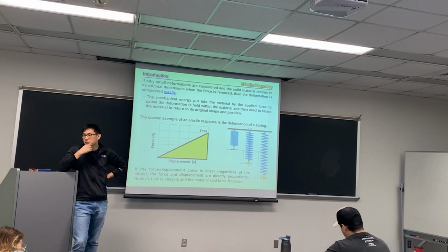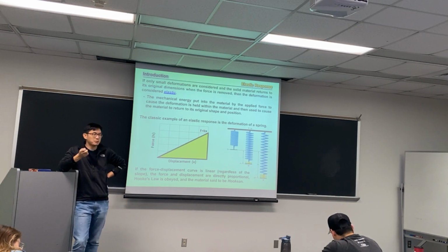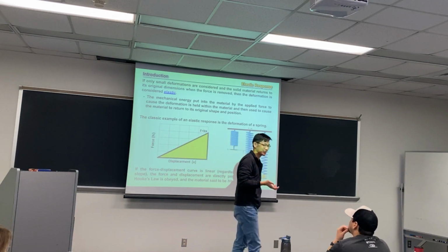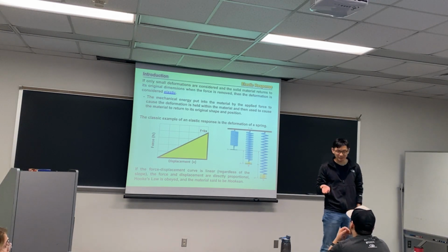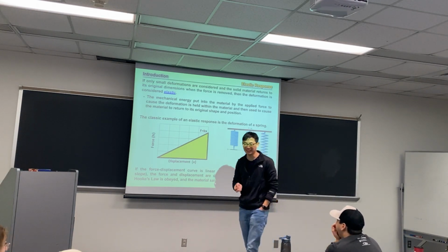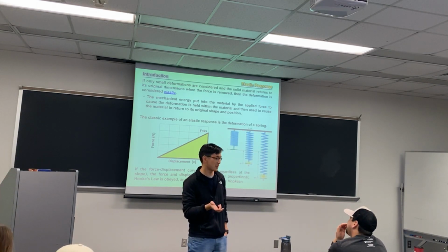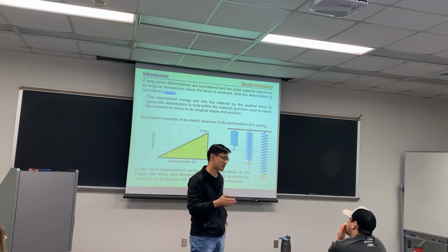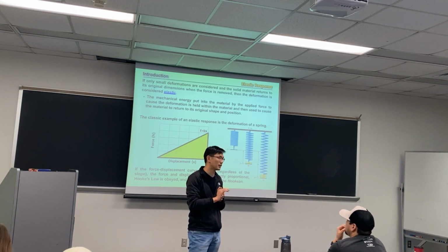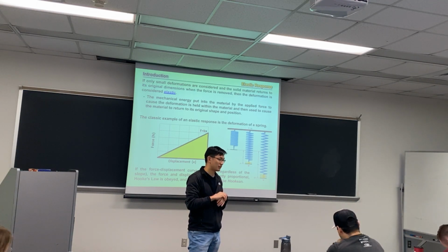And if your material is much softer, your modulus will be lower. Now, think about an example of a softer material. How about PDMS elastomer? Kilopascals? 0.1 gigapascal? All right, that's not the right answer. It was a good trap. It depends on cross-link density, and we will talk about how cross-link density affects modulus. Because elastomer is a very broad class, it can be made very soft or very rigid. But typically, they're only on the order of tens to hundreds of megapascal. Some of the soft ones can be even lower.